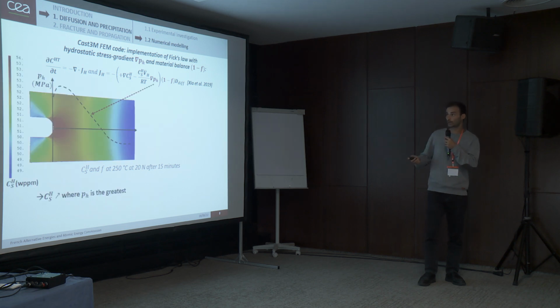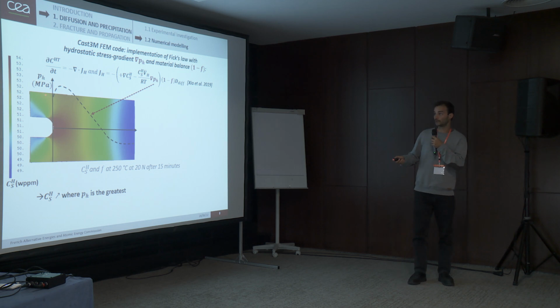To help understand the experimental observations and to quantify the cracking criteria and the hydride length, we implemented the diffusion and precipitation model in a finite element method code. It's a Fick's law with a hydrostatic stress gradient and a material balance with f, the hydride volume fraction. To show you some results, you can see here in the black curve the hydrostatic stress profile on the ligament, and you can see the hydrogen concentration in solid solution.